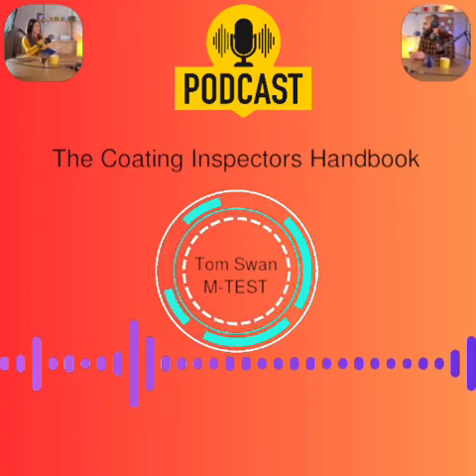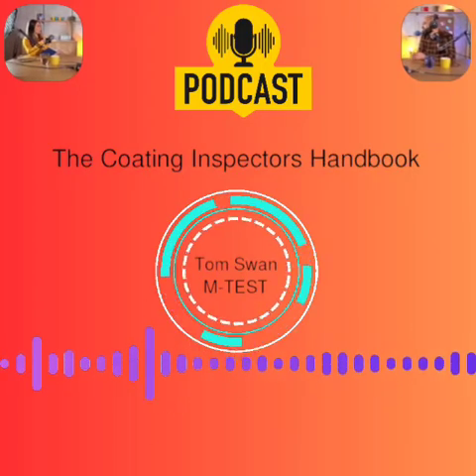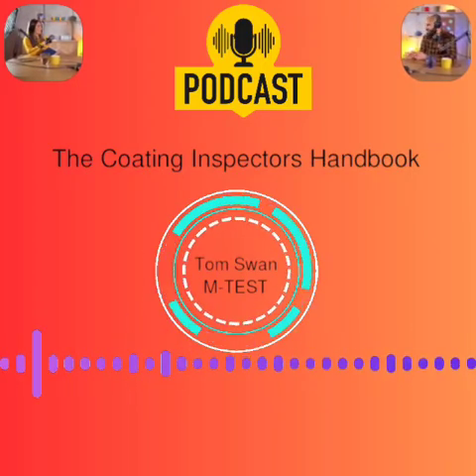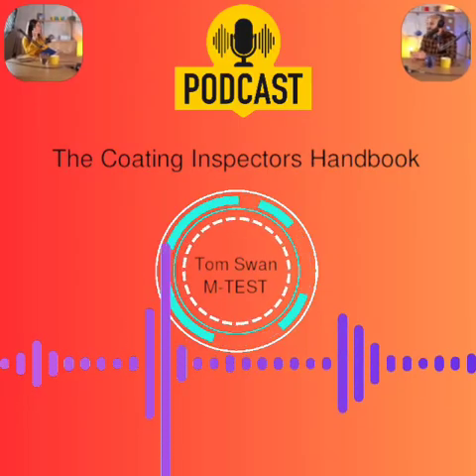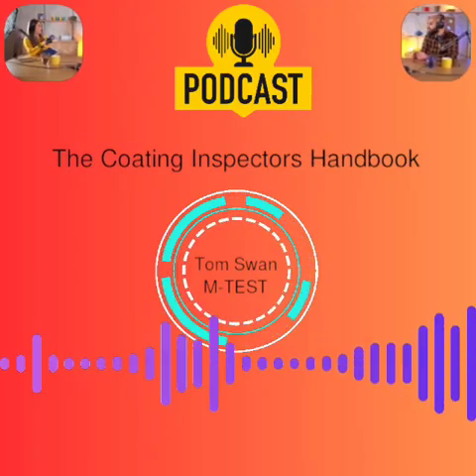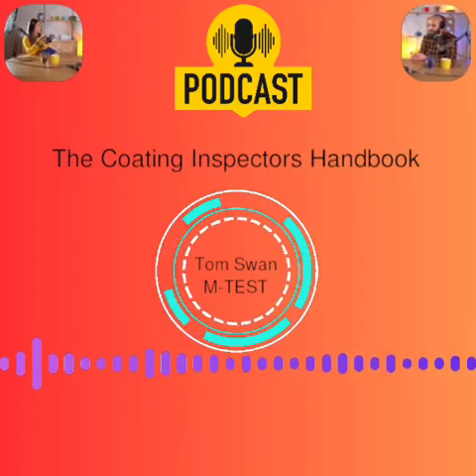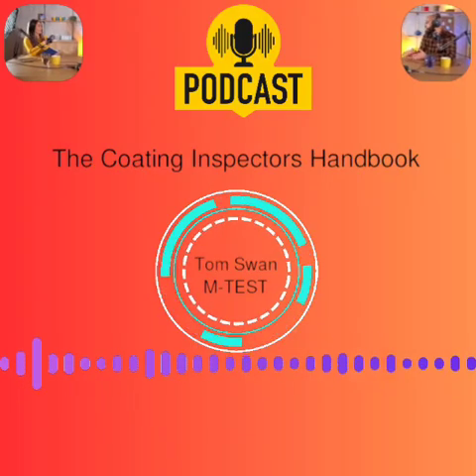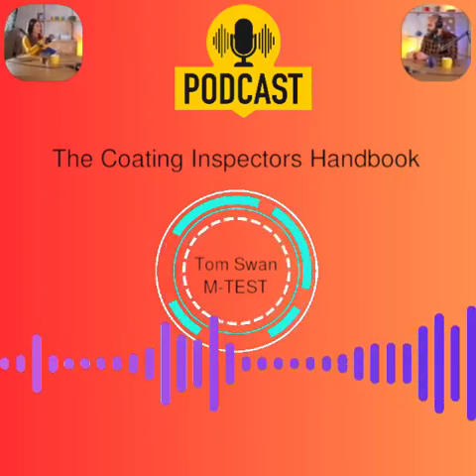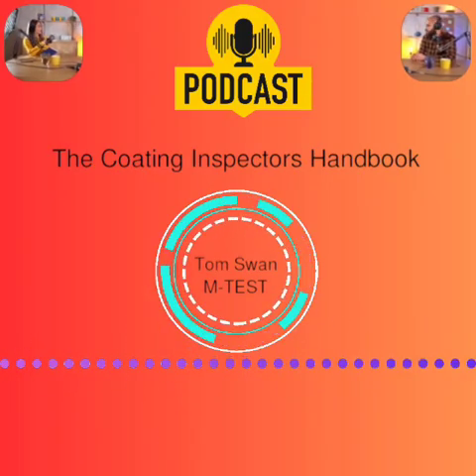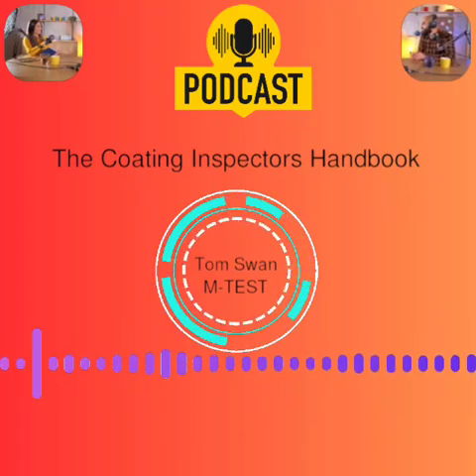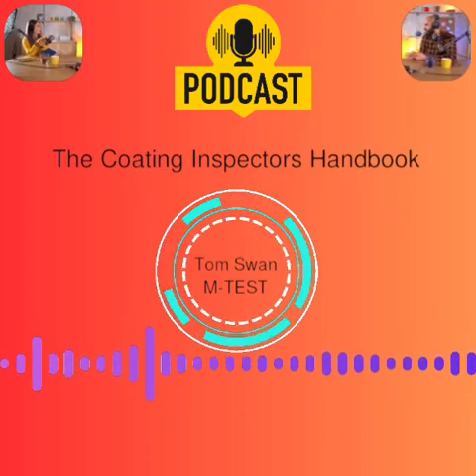You need that Goldilocks thickness. What if DFT is out of spec? First call the coating manufacturer's tech rep. Get their advice, preferably in writing, and don't argue over tenths of a mil, because of accuracy limits. Yeah, meter accuracy, 3 to 5% BMR variations. PA2 allows 20% on spots anyway. Rounding helps: nearest tenth for low DFT, maybe nearest half mil above 2-3 mils is practical.